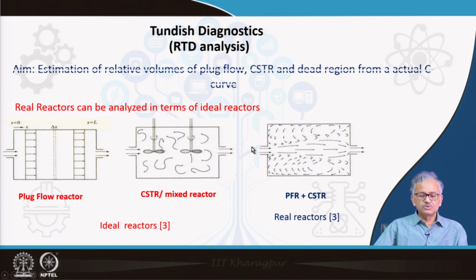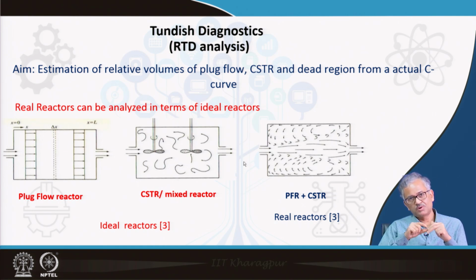Okay. So, in the tundish diagnostics, what is the aim basically? People estimate the relative volumes of the plug flow, CSTR and dead zone from the actual C curve. Basically, you have a curve called the C curve, and you can analyze it. The C curve is obtained by adding some amount of tracer, and at the exit you measure the tracer concentration with time. Then the dimensionless concentration, if you plot it against dimensionless time, gives the curve that is called the C curve.